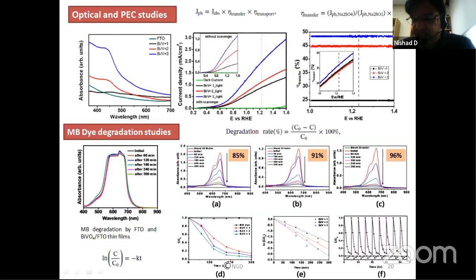So almost like 9 cycles it is quite stable. A very slight change is seen after 9 cycles. So this means that the photocorrosive properties of this material is also very good, and one can utilize this structure not only for the water splitting, but now for the water treatment also, where the dye degradation can be easily seen.